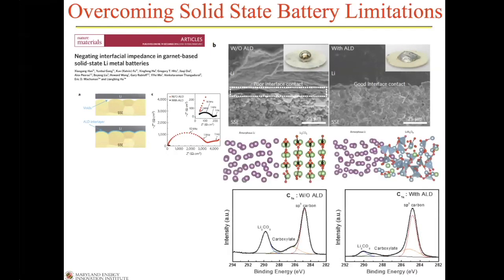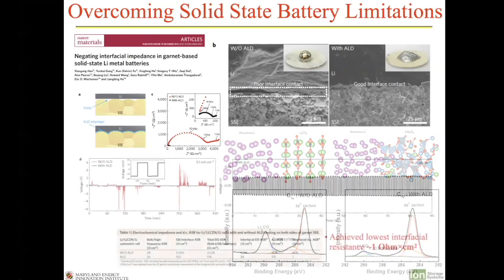The reason that we determine that's the case is that all of these garnet materials, they're lithium-conducting oxides, if exposed to even the smallest level of CO2, even in a glove box, it likes to form surface carbonates, and lithium metal just does not wet the carbonate. So we need to find ways to avoid forming a surface carbonate, and the ALD does that.